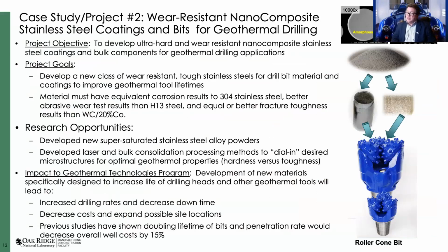One example of this was a funded geothermal project that we worked on a number of years ago. This was an earlier project, looking at iron-based amorphous alloy materials that we could fabricate in bulk as powders. In this case, we had done a lot of work with Carpenter to produce the powders. Then we could either take those powders and consolidate them into monolithic parts, or use laser directed energy deposition to deposit them and start making additive parts, or even cladded parts using these types of technologies. The benefit is that by creating this very fine microstructure, we could greatly increase the hardness values, as well as improve wear resistance and corrosion. These were compositions that we knew, as they devitrified and crystallized, would become stainless steels, and we wanted to look at them for these types of applications.